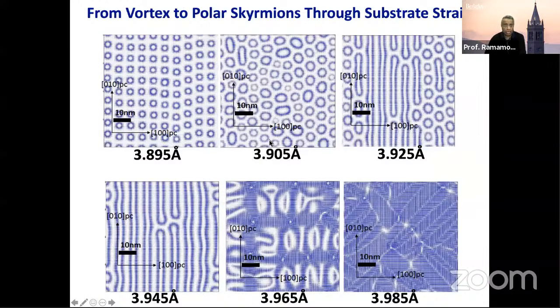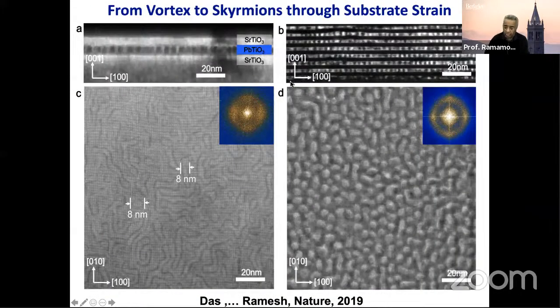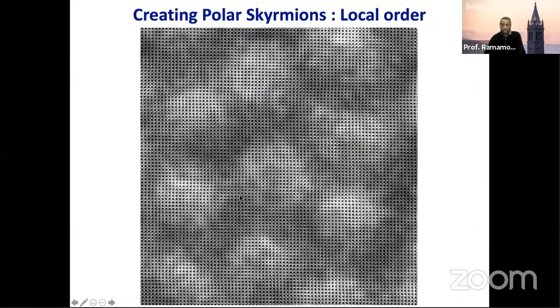These are the calculations from phase field calculations. Ab initio showed essentially the same, that if you go to strontium titanate, you should start to see these bubbles. It took us a while to get there because the experiments were very complicated. But sure enough, if you grow these superlattices on a different substrate, you could start to see these bubble-like features. Let me blow it up a little bit more. These are the polar skyrmions. They're about 5 to 6 nanometers in diameter, of the order of maybe 16 to 18 unit cells.